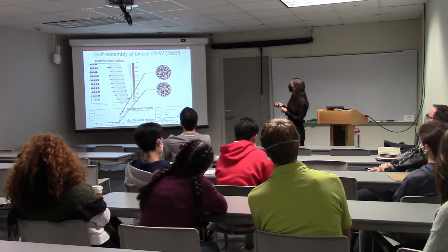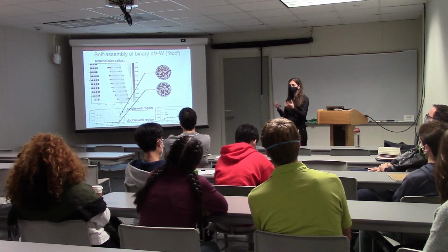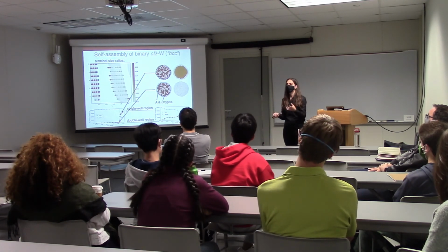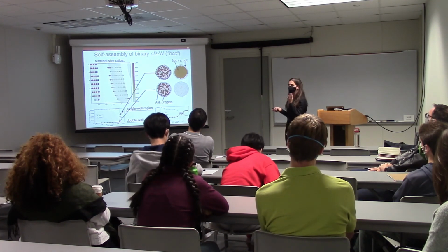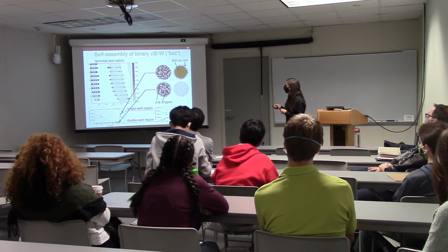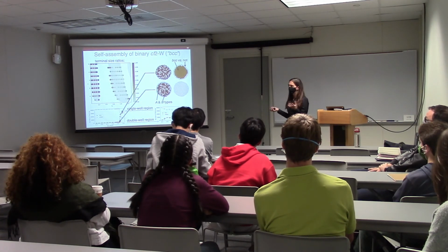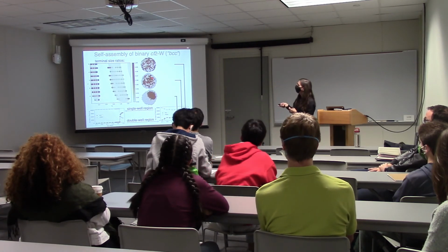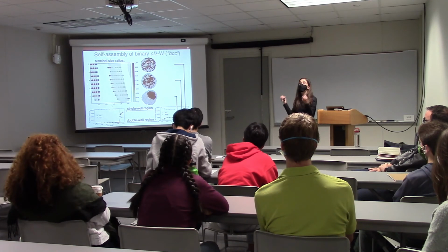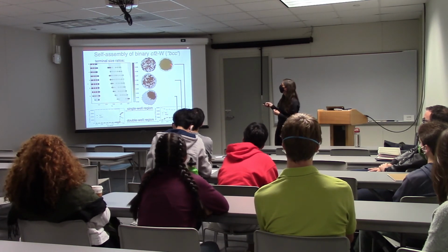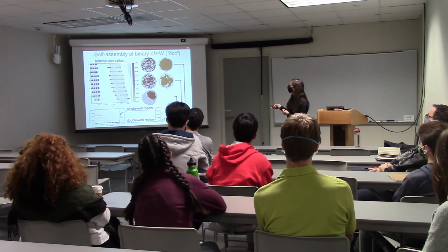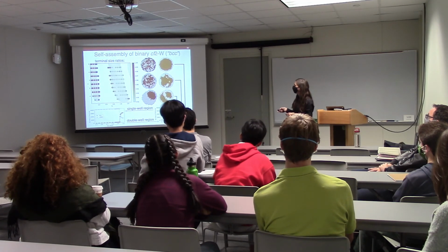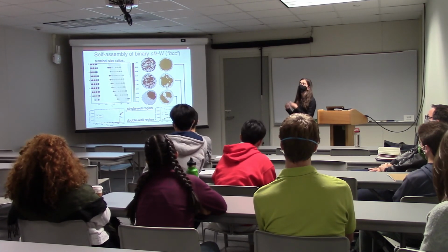So in the single well region, here you see the two different types of particles highlighted, A and B type, and on the right you see which particles are in the correct structure. If it's yellow, it's BCC; if it's whitish, it's not, which means after the step down, no particle is in the right environment. Pretty boring. In the double well region, you can already see that here gradually and here completely, those two sizes demix. And ultimately, you have your correct crystal structure here in full bulk. Here you see that the disorder impinges on the crystal more and more, but ultimately both of them actually crystallize in the correct structure, only separately.